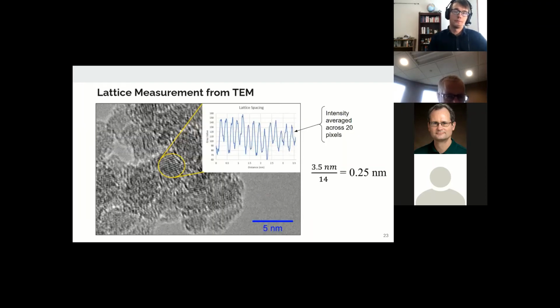From TEM images, we can measure both the particle size by measuring the diameter of the particles directly, and the lattice spacing of the particles to confirm that the powder is indeed silicon carbide and to determine which polymorph of silicon carbide we have.